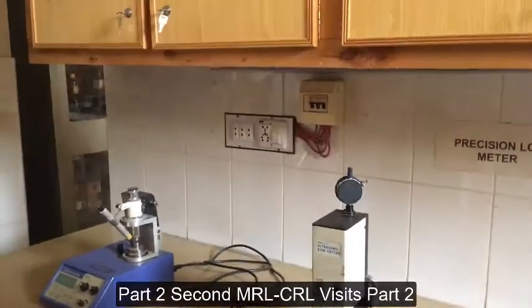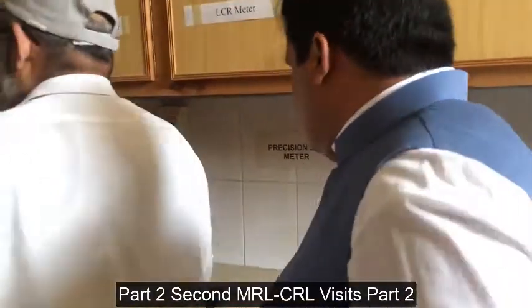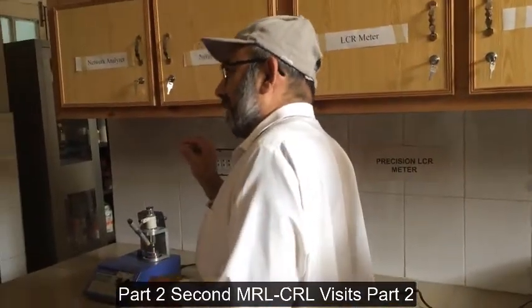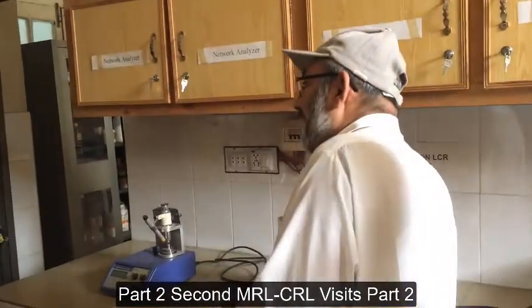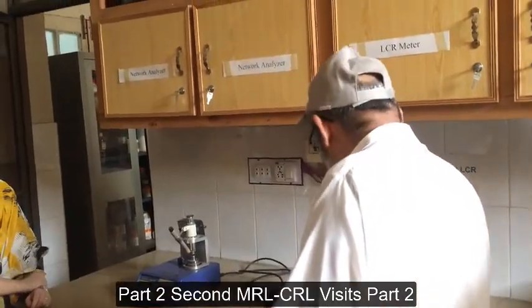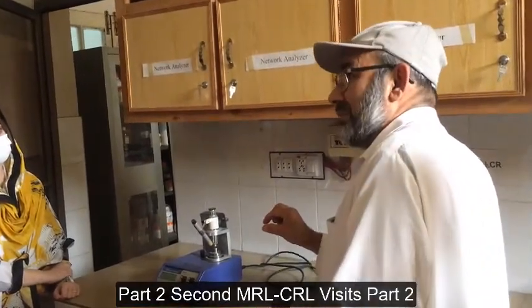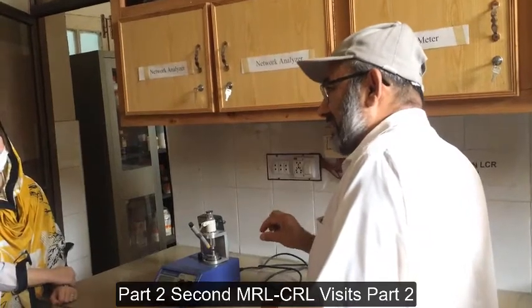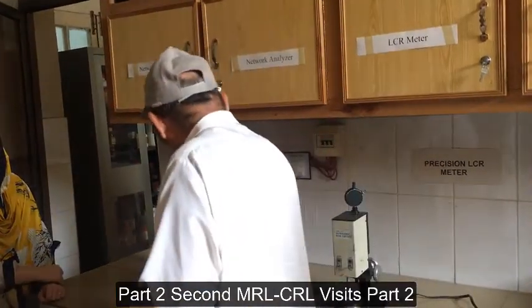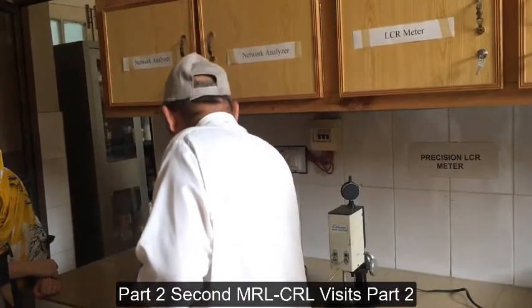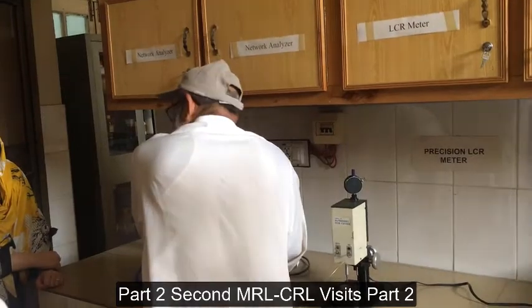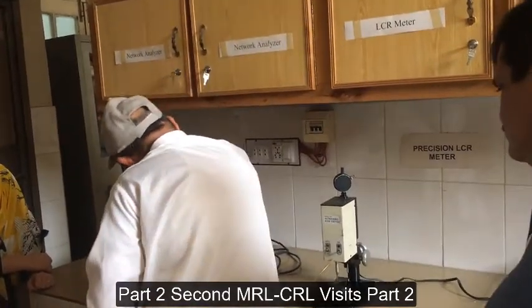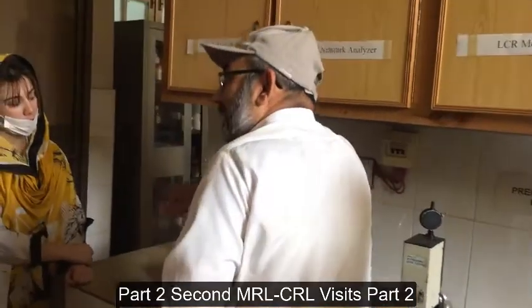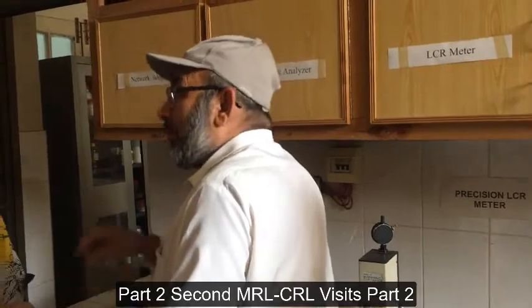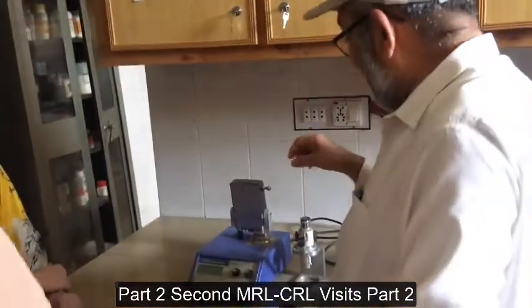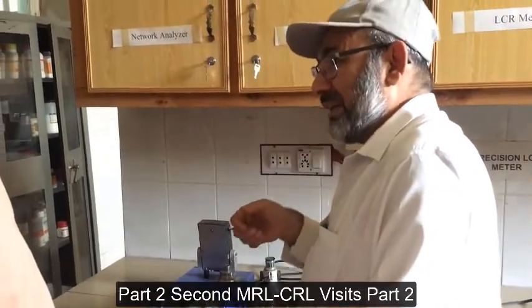When you are making electron microscope samples, you thin the material up to 100 micron thickness. Then you bring it here and drill it. This is an ultrasonic drill. It gives you a 3 millimeter diameter disc, which is 100 micron thick. Then you bring it here and fix the material, stick it here, and it rotates, and this wheel is upon it. So it dimples the middle of the material up to 25 micron. When it is dimpled, you can measure with an optical microscope how much the material has been dimpled.